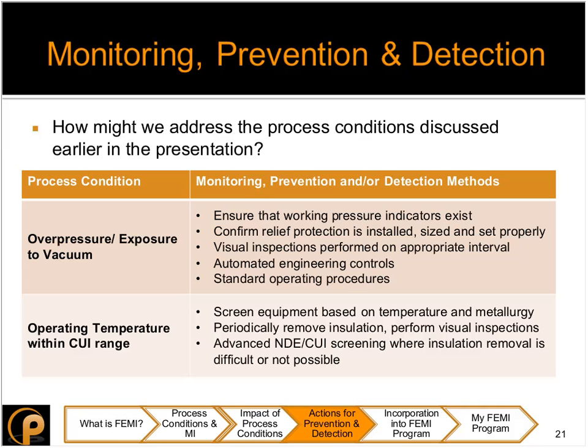The next scenario is operating within the corrosion under insulation range. It's important to screen the equipment based upon the temperature that you're operating at and your metallurgy, whether it's carbon steel or stainless steel, within that temperature range that I described in the previous slides. The next step is to periodically remove insulation and perform visual inspection so that you ensure that there are no leaks on the system that are caused due to CUI. But as I said, this might be a more expensive process, and you might have to build scaffolding and access requirements where piping and equipment cannot be easily accessed.